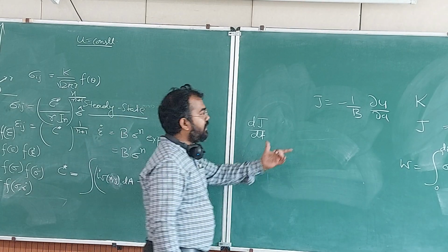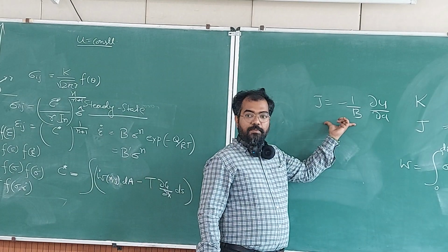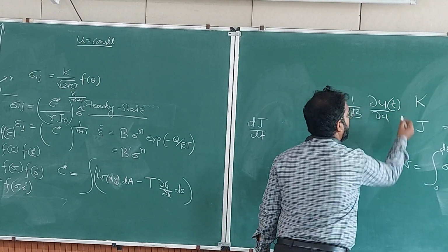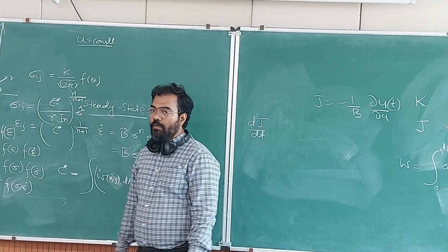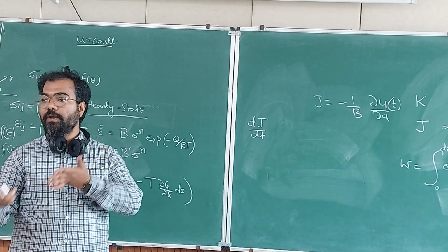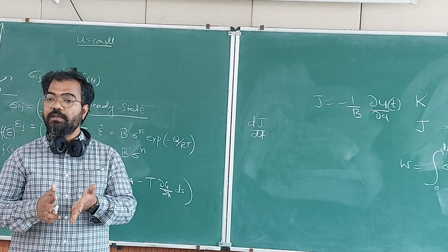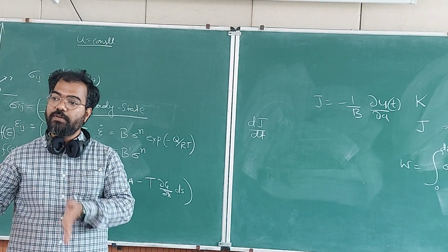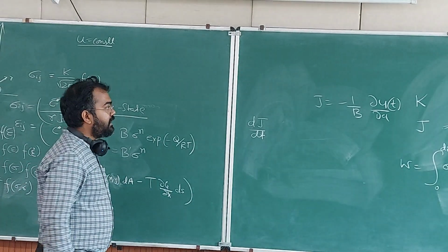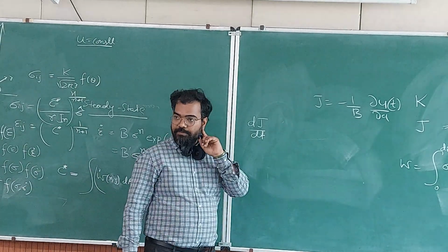Okay, so this quantity will now be a function of time, because U will be a function of time. So the amount of energy which is released when you go from A to A plus delta A will be different if you load it for different times. Okay. So per unit time, that must be defining that rate.